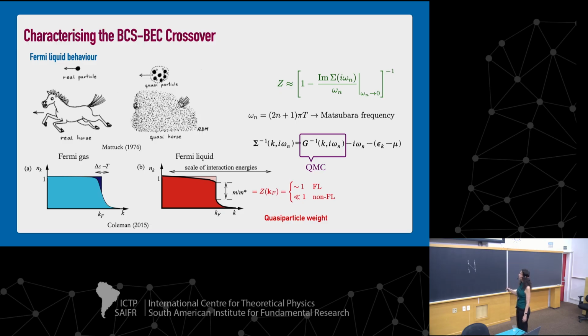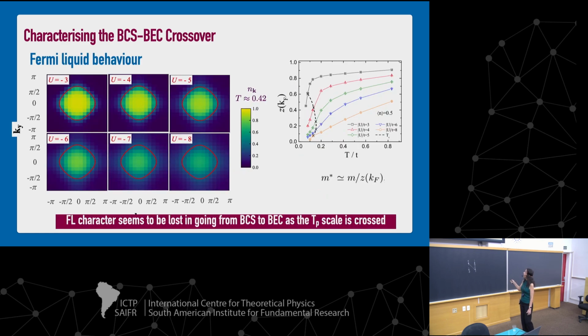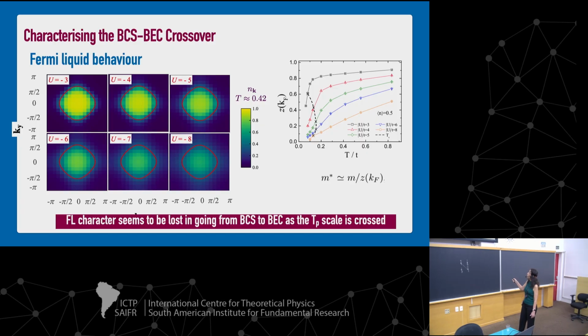And usually what is done is looking at the quasi-particle weight, which is constant here. And this is something we can calculate within Quantum Monte Carlo. It's not straightforward, but it can be done. And this is what we actually did. And so this is the quasi-particle weight, and we are marking its value here along the critical temperature. And we see that the Fermi liquid seems to be lost along this crossover when the pairing temperature scale is crossed.